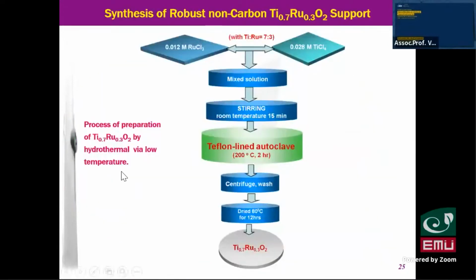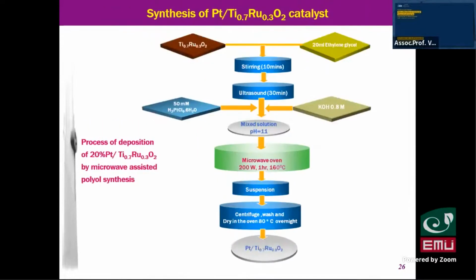This is the synthesis of our support. We applied a hydrothermal process similar to the first approach. We synthesized the material with ruthenium doped into titanium oxide, and also dispersed platinum on the ruthenium titanium oxide.